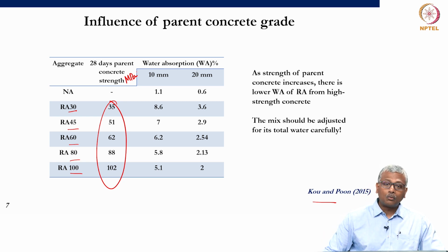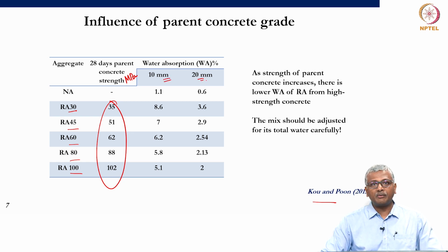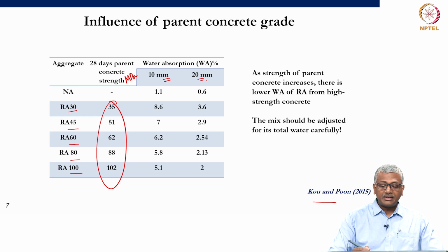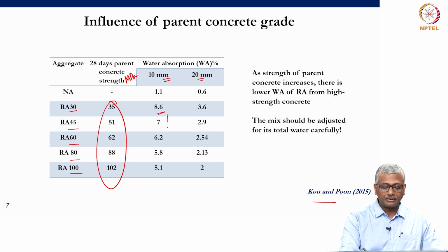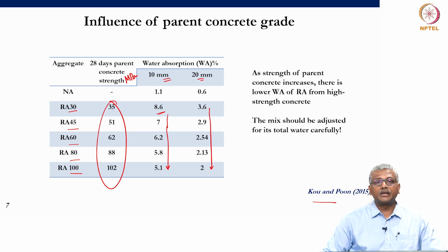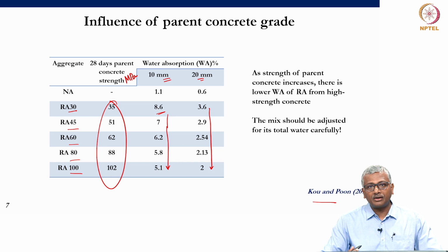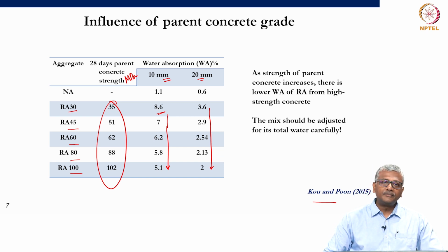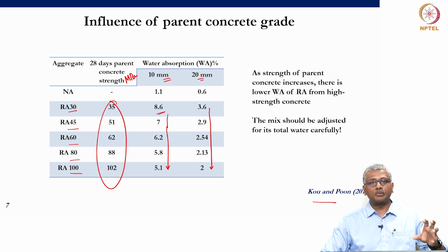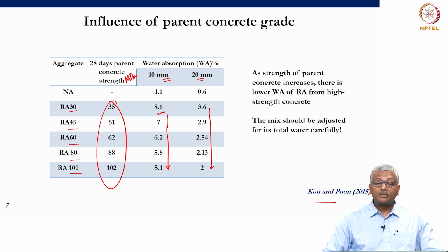So, you see here that the water absorption of the 10 mm and 20 mm aggregate that you produce out of this is significantly changing, right. For instance, from 8.6, it goes down to 5.1. From 3.6, it is going down to 2. That means the higher the grade of the parent concrete, the lower is the water absorption of the coarse aggregates that you produce from it. Okay.